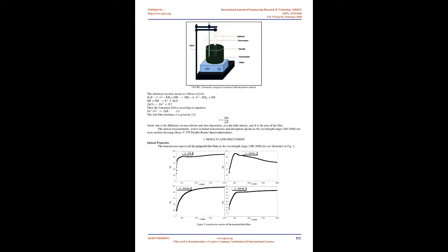2. Experimental. ZnS thin films were deposited on glass substrates by chemical bath deposition technique. The cleaning of substrate plays an important role in deposition of thin film by CBD process. The substrates were cleaned with a soapy solution, rinsed with distilled water and then with nitric acid followed by isopropanol, kept in an ultrasonic bath and finally rinsed with deionized water and dried in the air.